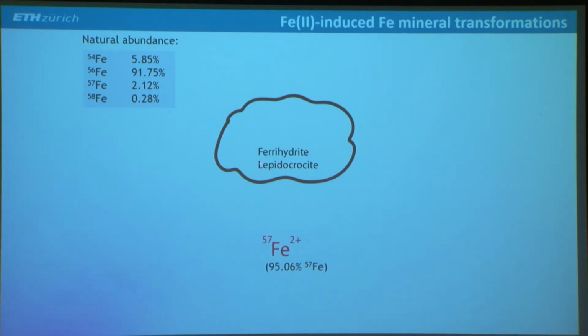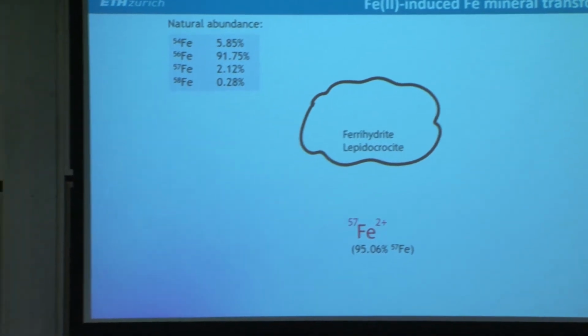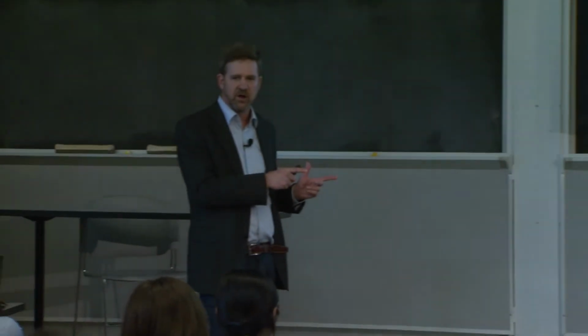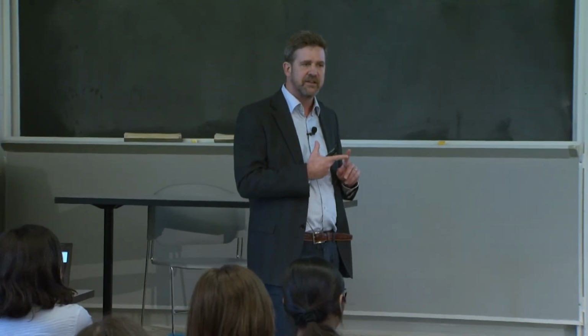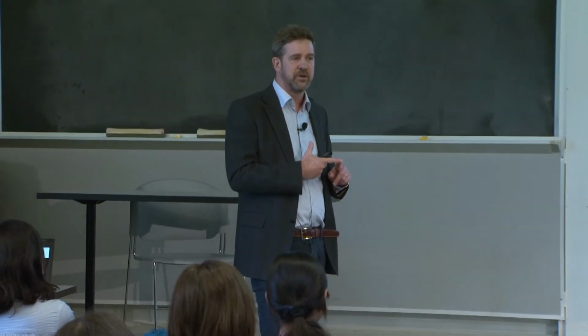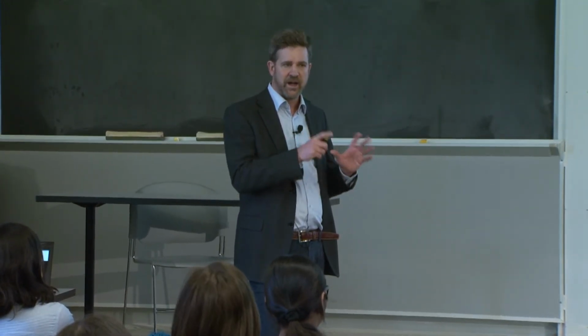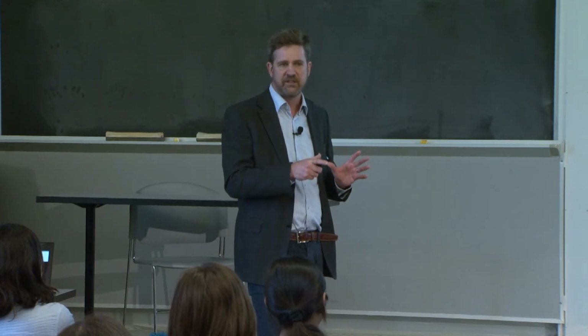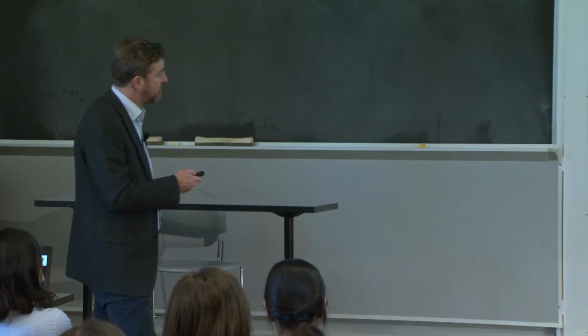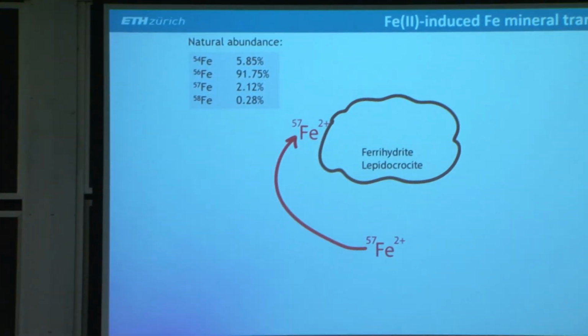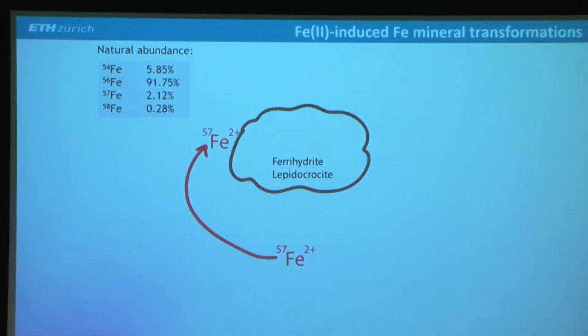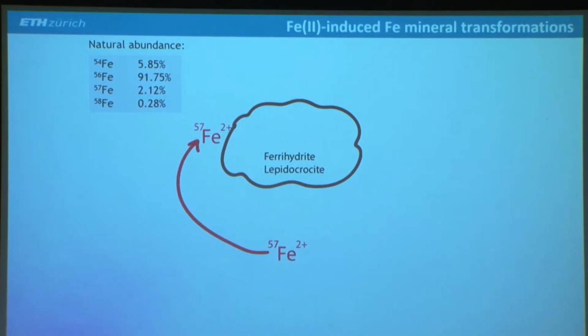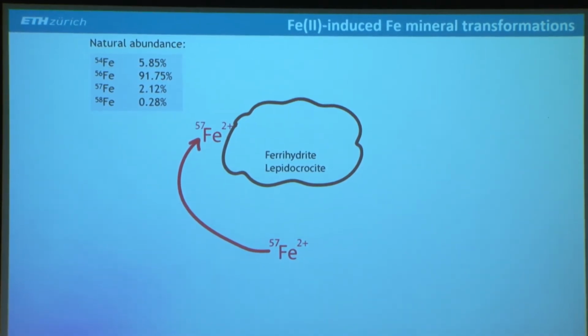And we spike the iron 57 here for two reasons. One is that we are able to follow the kinetics of atom exchange between the spiked iron and the floc iron. And the second is that iron 57 is Mössbauer active, so we can also follow where it goes or what type of mineral it forms. Okay, so what could happen is that this iron could get adsorbed to the floc material. This will be a pH-dependent process, of course. So at high pH, we have more sorption. At low pH, we have less sorption.